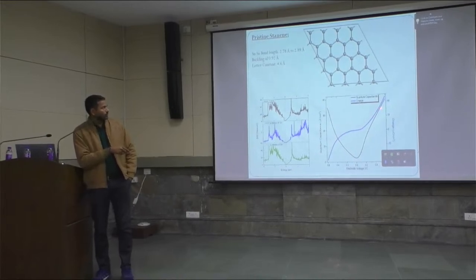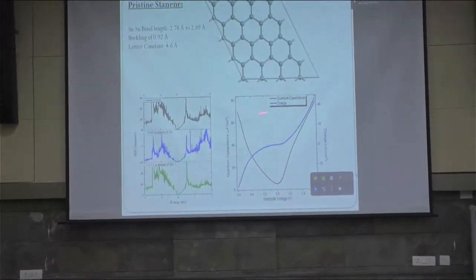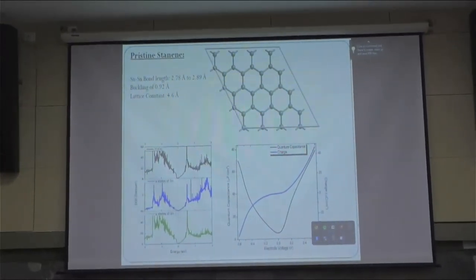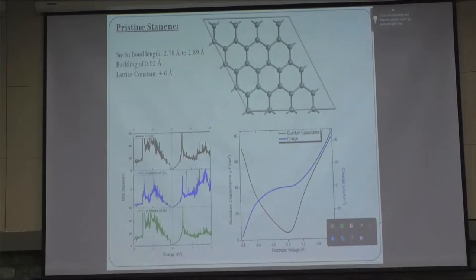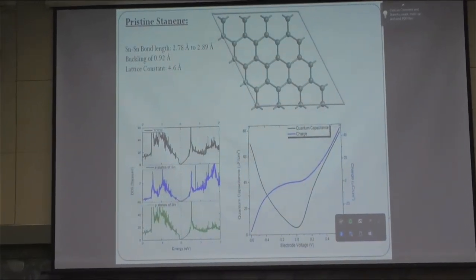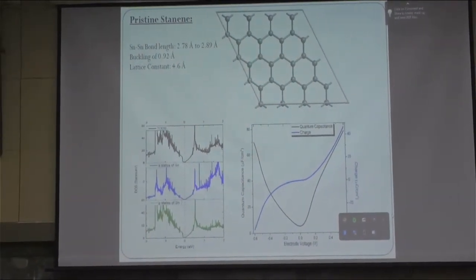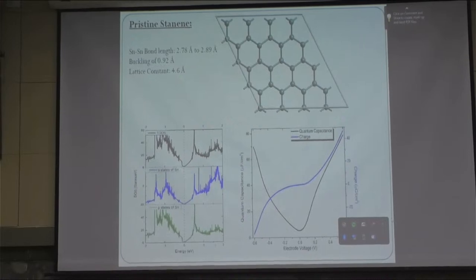And this is the quantum capacitance curve for pristine stanene and the charge storage curve also. The quantum capacitance offered by the pristine stanene is around 77 microfarad per centimeter square, which is about 7 times higher than pristine graphene. So stanene offers around 7 times higher quantum capacitance than graphene.